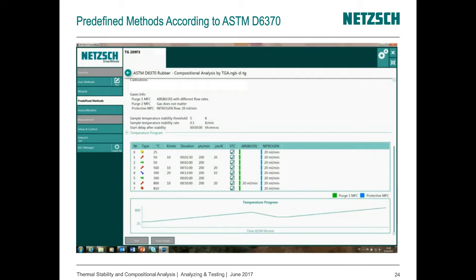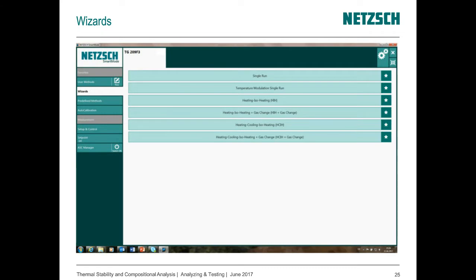But of course, if we don't want to use such a predefined method, we can also make our own temperature program. For example, by using wizards. And here on this list, you can see several wizards which are available. And if we think back to the example where we have separated the amount of added carbon black from the amount of pyrolytic carbon, then we had a special temperature program, heating, cooling, isothermal heating, and the second heating step was under air or under oxidizing conditions.